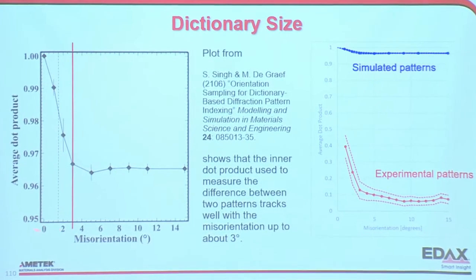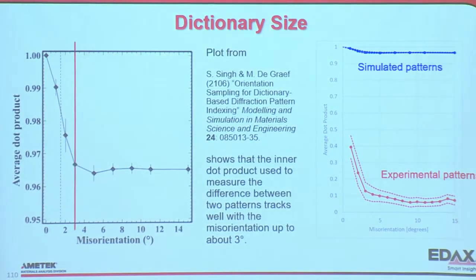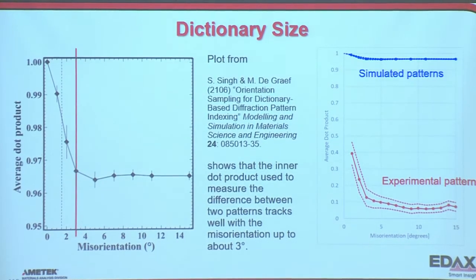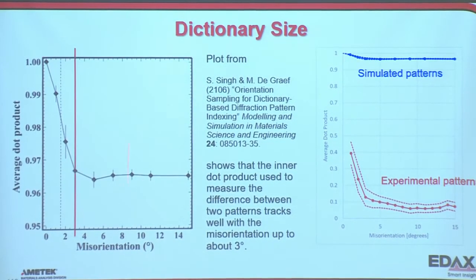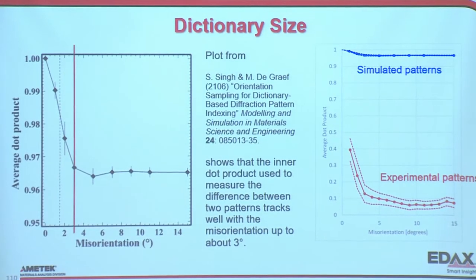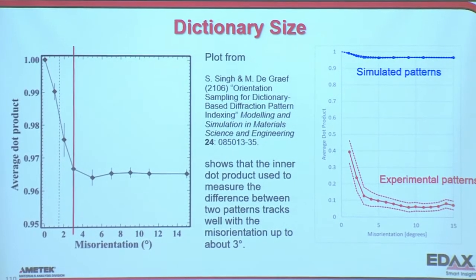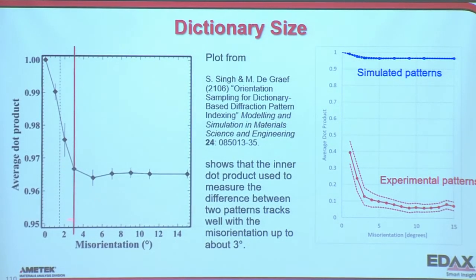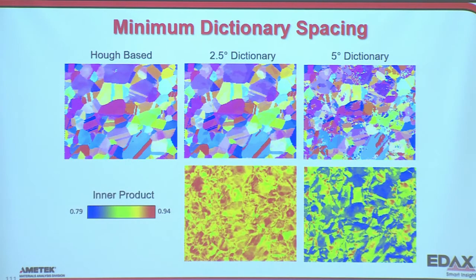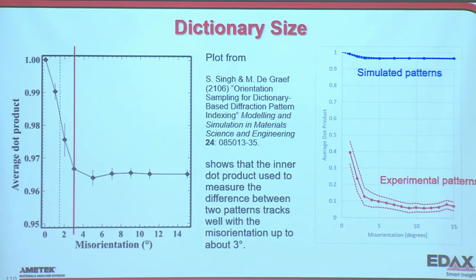What we find is with the sampling, with the technique we're using to compare patterns, it's good out to about 3 degrees. After that, we can't really compare patterns. After that, they're all different. We don't know how different, but we do know they're different. With low misorientations, it actually tracks this measure, because we're not indexing, so we don't know this misorientation. We've had to calculate this a different way.